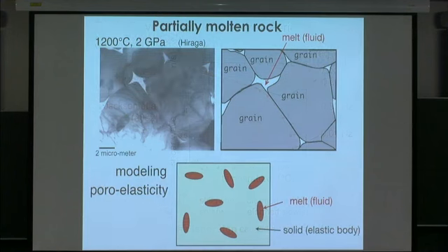One of the most important sources of rock anelasticity is slip at grain boundaries. Grain boundary is weaker than grain inside, so if temperature is high enough and the deformation is slow enough, grain boundary cannot sustain the applied shear stress and slips a bit, causing a further deformation of the aggregate.